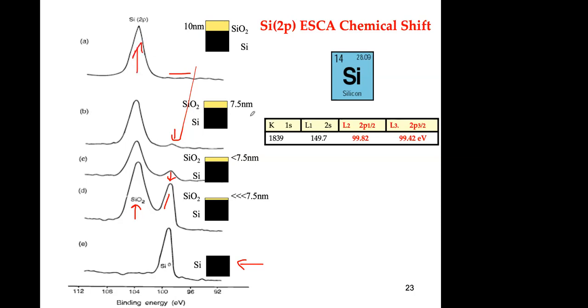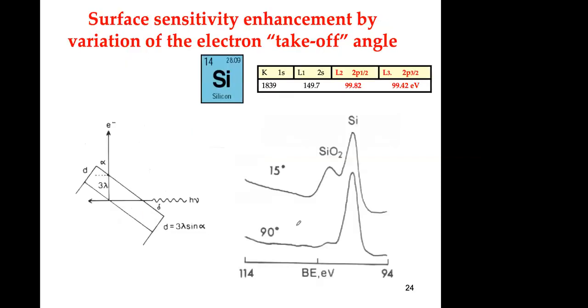So this is a way to analyze surface. It's a very surface sensitive technique. And you can see that very easily, and you can determine the thickness of the samples. I mean, of the oxides, for example. You can do it differently. You can do it by changing the angle of detection.